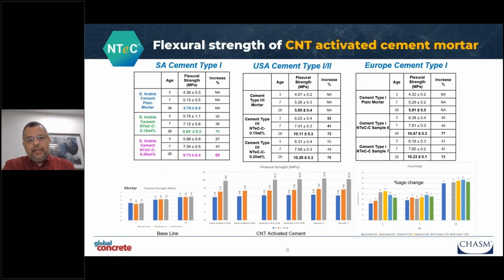And what came out was very interesting. If you look at the flexural strength, with this being the baseline, you would see almost across the board the flexural strength moved up by 70 to 80%. Of course, in my previous chart, I showed a 100% increase with the liquid dispersion. The solid dispersion takes a beating, but still you are at a 70% level, which is considerable. And this is across various grades of cement from across the globe. It's as high as 75%.